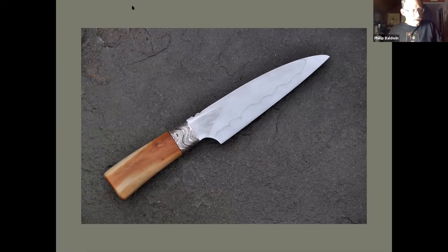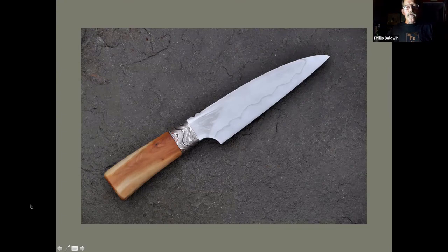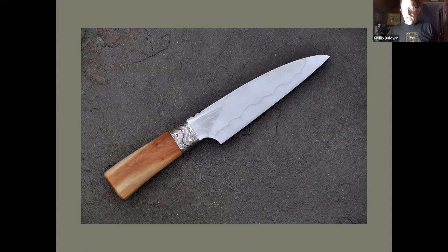If it's too hard, given a certain edge geometry, then the edge will flake or chip. If it's too soft, it'll fold or wear pretty quickly. When I'm doing this, I tend to start out with the blade too hard, test it, and then gradually soften it until I get the performance that I want. If I never get the performance I want, it means that the blade has been overheated, and the crystalline structure is too large and it'll never be any good, in which case I'll throw it out. That's just how I do it.